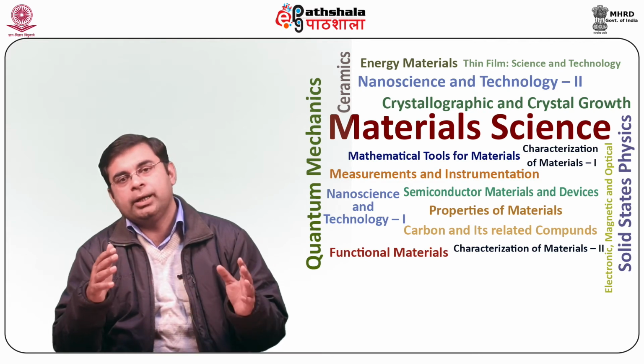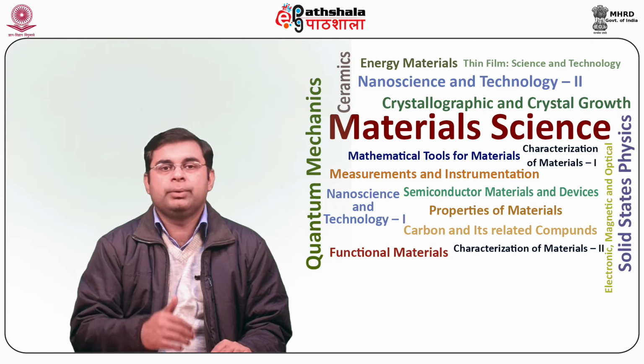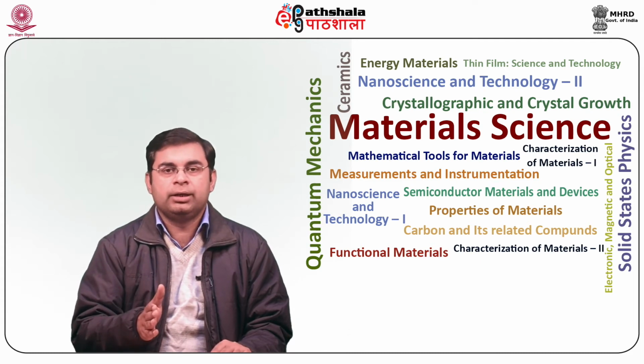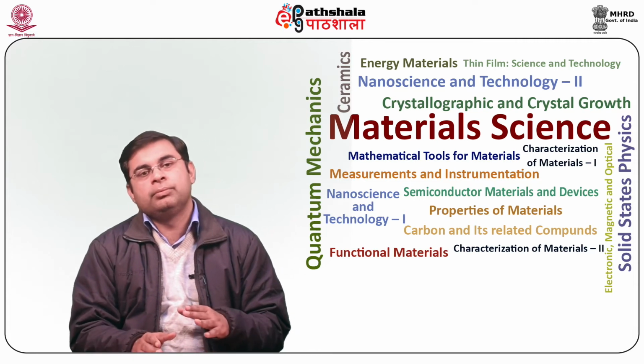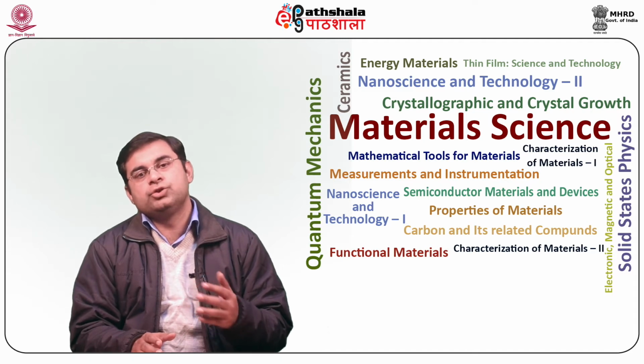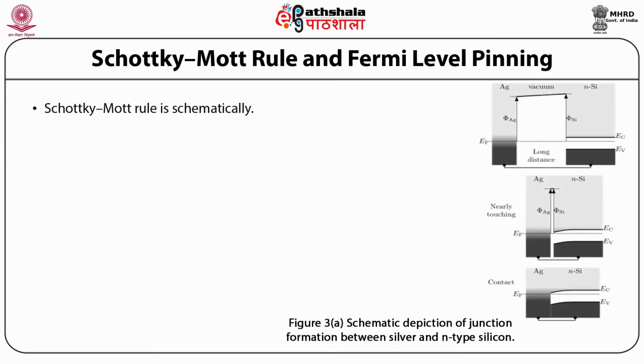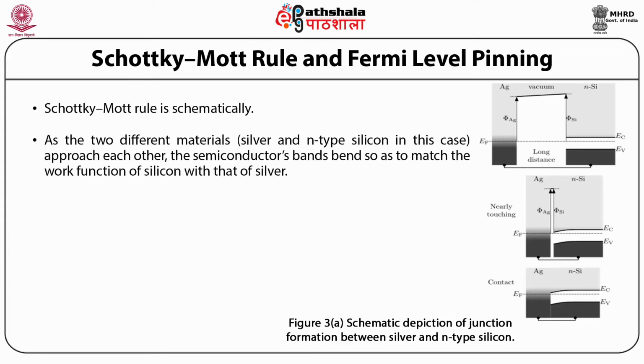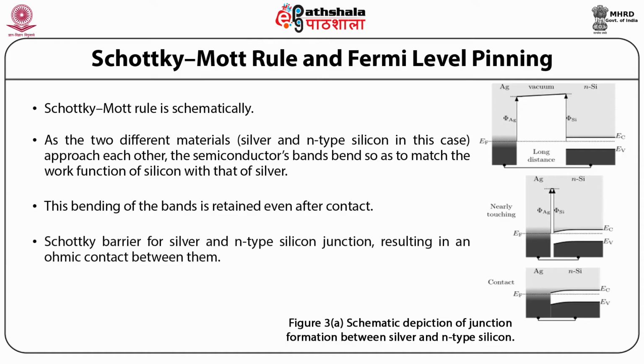This problem can be alleviated by including additional processes, for example, addition of an insulating intermediate layer to unpin the bands. Germanium nitride insulation is usually used in the case of germanium. The Schottky-Mott rule is schematically shown in figure 3a as the two different materials, silver and n-type silicon in this case, approach each other. Semiconductors bend so as to match the work function of silicon with that of silver. This bending of bands is retained even after the contact. This model envisages a very small Schottky barrier for the silver and n-type silicon junction, resulting in an ohmic contact between them.